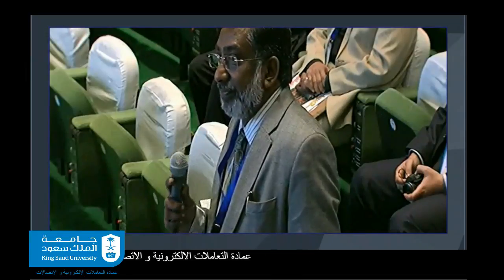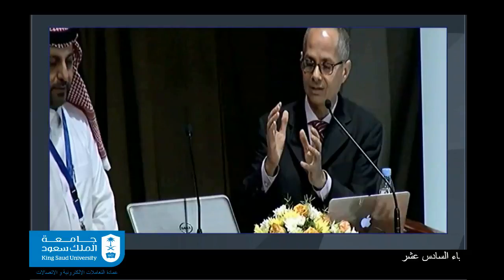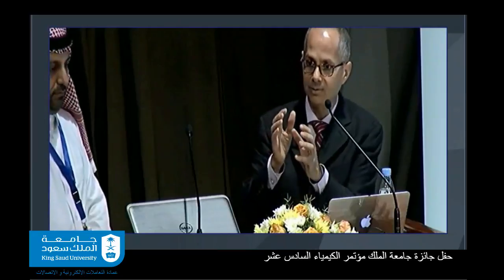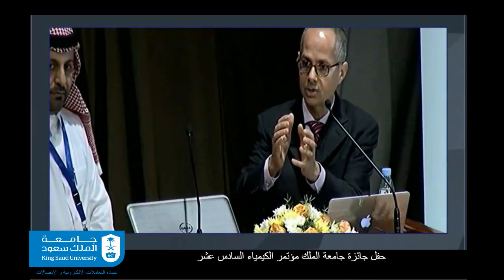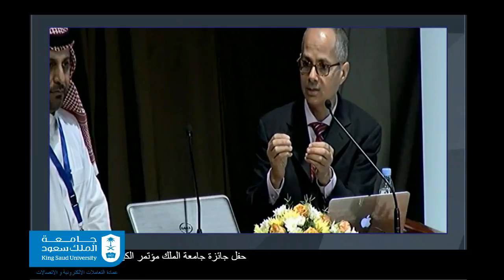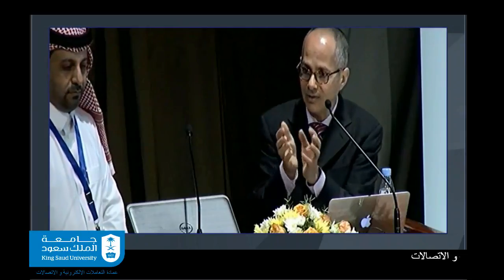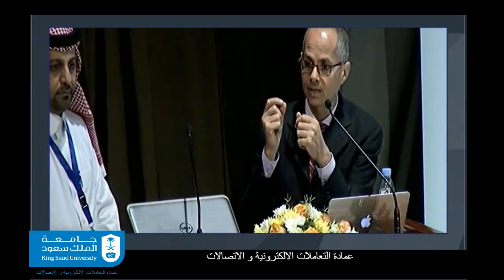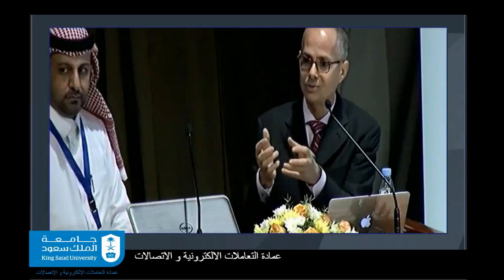Got it. Now remember, the enzyme is made from these amino acid chains that prop the active site into place. So I think what's going on in the MOF is that we used the MOF backbone to prop the active site into position with the right chemical functionality and the distance between those chemical functionalities to have the same kind of selectivity. So it makes me think that the MOF is really a nice flexible backbone. We should not think about the MOF as a very rigid framework, although it is architecturally robust. It's made of molecules, and molecules wiggle. So there's a lot of give in the backbone.